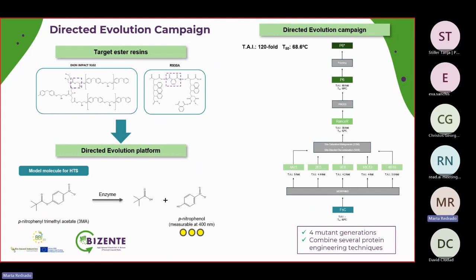To start the directed evolution platform, we had to select a model molecule, and that was the p-nitrophenyl trimethyl acetate, which was selected because it has a structure pretty similar to that of the ester resins. It was used for the HTS, the high throughput screening, and it was really easy to follow the hydrolysis because it releases a colorimetric, yellow compound that can be followed.